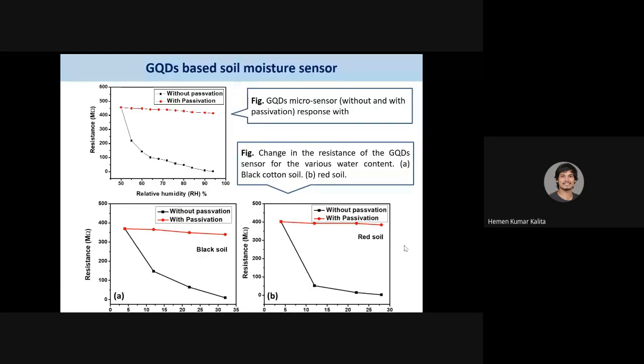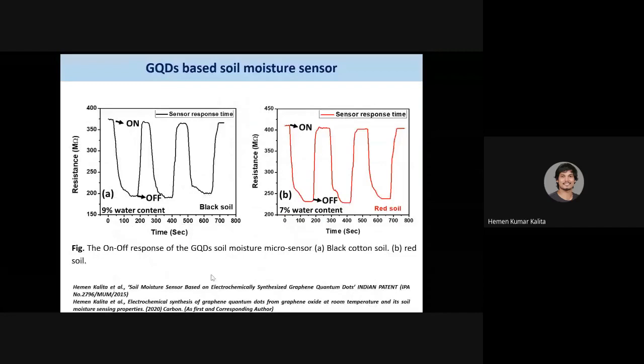Now in the sensor, there are many parameters, and one of the most important parameters is response time, that is the on-off ratio, response time and the recovery time. For this we have tried to calculate the response time of the sensor. Obviously we have tried to do the response calculation at a very low water content soil, because if our sensor is working absolutely fine for low water content, then it will obviously work for higher water content as well. That's the whole purpose, to measure the response for a very low water content. We have measured for 9% and 7% water content in our case.